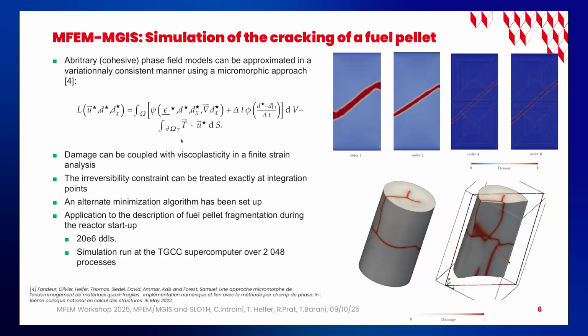And we leverage MFEM-MGIS to use this micromorphic approach to rupture to describe various kinds of things and couple damage with viscoplasticity and finite strain analysis. The most important point regarding the phase field approach to rupture is that the irreversibility constraint can be treated exactly at the integration points.